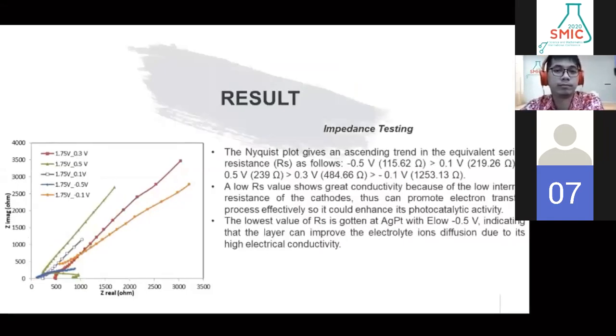Next is impedance testing. On the left side, the Nyquist plot gives an ascending trend in the equivalent series resistance, or RS, as follows. A low RS value shows great conductivity because of the low internal resistance of the cathodes. This can promote the electron transfer process effectively, so it could enhance its photocatalytic activity. And the lowest value of RS is obtained at AgPt with E low minus 0.5 volt, indicating that the layer can improve the electrolyte ion diffusion due to its higher electrical conductivity.